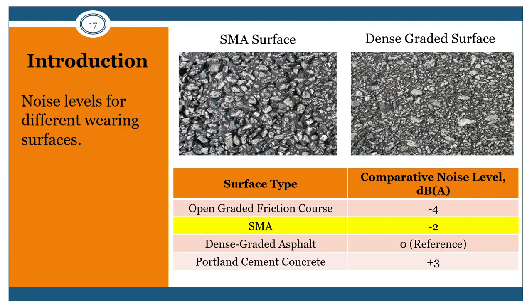In comparison, open graded friction courses have a 4 decibel lower noise level in comparison to the dense graded asphalt surfaces. So SMA as well as open graded friction courses are generally quieter than the standard dense graded asphalt mixtures on the surface. The photograph on the upper left shows the coarse surface texture, or the macro surface texture, of an SMA surface as compared to the macro surface texture of a dense graded surface itself. The macro surface texture is one of the reasons for the lower noise level in comparison to the dense graded asphalt surface.